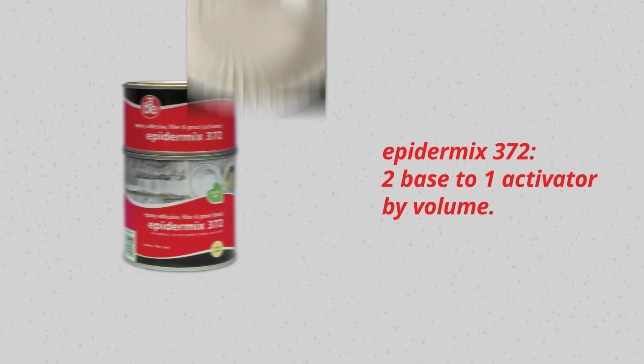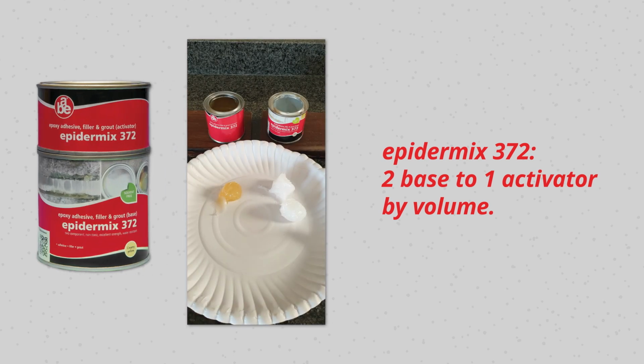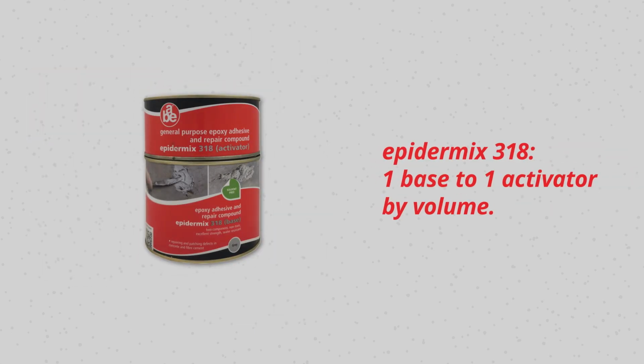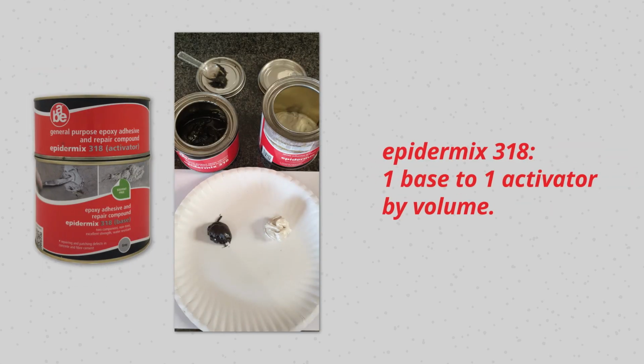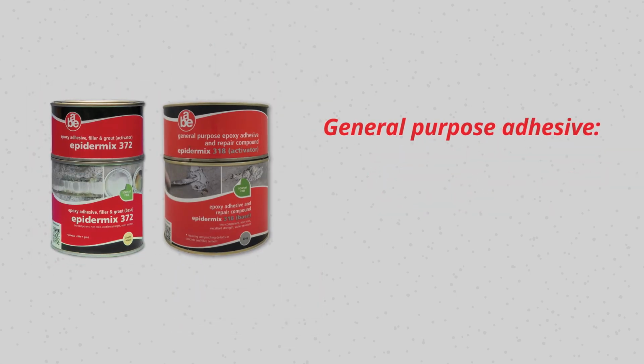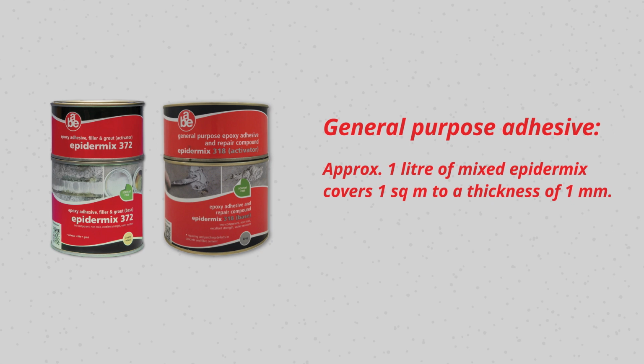Epidermix 372 should be mixed by a volume of 2 base to 1 activator. Epidermix 318 should be mixed by a volume of 1 base to 1 activator. As a general purpose adhesive, approximately 1 liter of mixed Epidermix covers 1 square meter to a thickness of 1 millimeter.